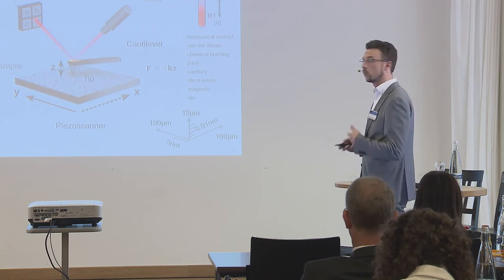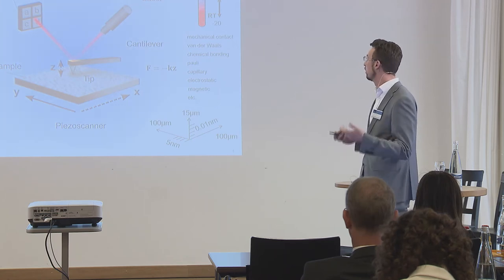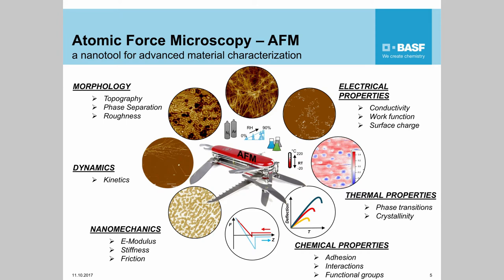Atomic force microscopy is very versatile. We can heat our samples, measure at elevated temperatures, measure in liquids, which is really cool for studying adsorption of polymers on surfaces. We can measure in argon-nitrogen if you want to work oxygen-free, water-free, and also at different humidities. Besides morphology measurements, we can characterize electronic properties using conducting tips and measure thermal properties using microstructure tips which we can heat, and therefore measure local melting points of surfaces.